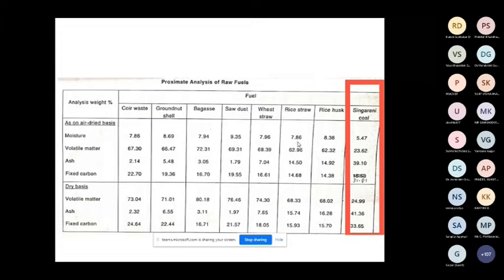If you compare the volatile matter, it is almost 3 times that of coal. Coal has 23.6% volatile matter, whereas the biomass fuels in this study had 67, 66, 72, 69, 68. Almost 3 times the value of coal. Highly volatile. Then ash content varies from 2% to around 14 or 15%.